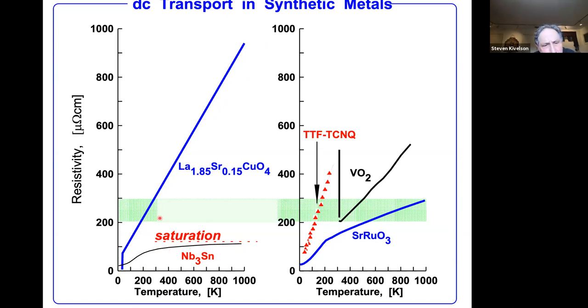But the thing that I think is more important than this is that this resistivity continues to increase with temperature. It increases up to a value. So let me put my version. This is the quantum of resistance. This is where resistivity saturation occurs in niobium-3 tin. And what you see is that lanthanum strontium copper oxide simply doesn't seem to know about this. It punches through this and goes to very high values, values that you would have said should be characteristic of an insulator, were it not for the fact that the resistivity is an increasing function of temperature.